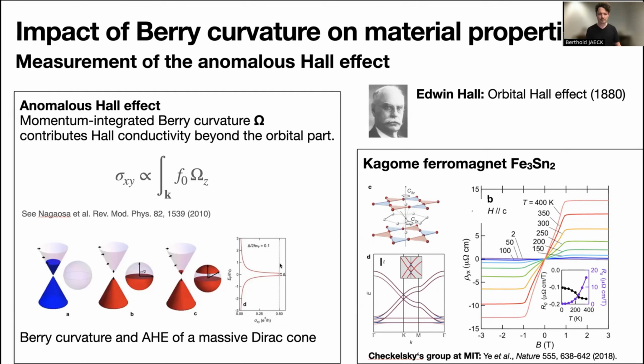So the idea of using the anomalous Hall effect to study topological materials obviously has been around for many years and also found entry into the study of Kagome systems. And I think most notable, the first work that really showcased this relation was done by Joe Checkelsky's group back in 2018, when they could show that the Dirac cone of Fe3Sn2 can give rise to a quite sizable anomalous Hall effect in the electrical transport properties.